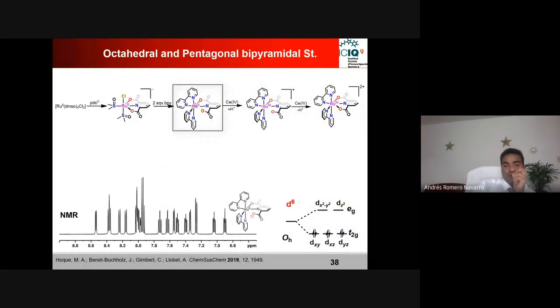I have synthesized this molecule, a ruthenium-2 with 2 bipyridine ligands and then this pyridine carboxylate. So this is a 6-coordinated octahedral geometry of this ruthenium compound. And as you can see, this is the orbital splitting pattern. From here, you can see that it is a diamagnetic molecule because you don't have any unpaired electron present in the system, and that you can characterize by NMR. That is the technique to characterize this catalyst. And then if you oxidize this ruthenium-2 by 1 electron, you can generate this ruthenium-3 and isolate it. And a further 1 electron oxidation can give you this ruthenium-4 compound.